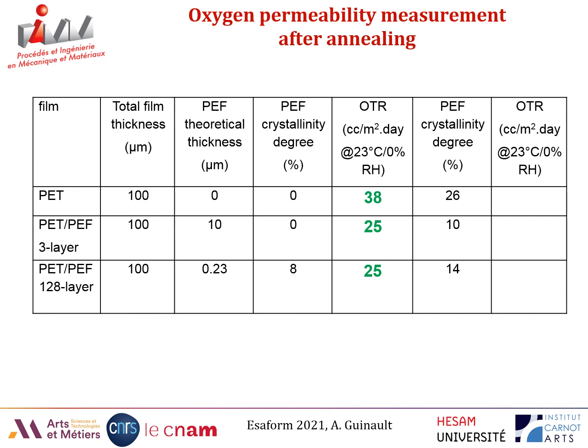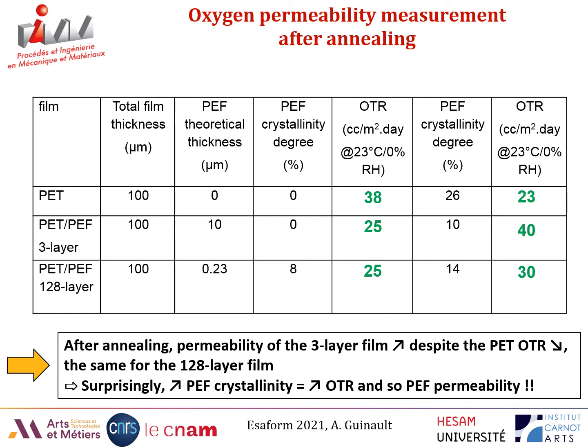Now we can see the effect of the annealing and the increase of crystallinity on the gas barrier properties of the films. So you can see that for PET, when you do an annealing, you decrease the oxygen transmission rate from 38 cc per meter square per day to 23. But for PET-PEF 3-layer and PET-PEF 128-layer, the value finally doesn't decrease but increases. So after annealing, you can see that surprisingly, if you increase PEF crystallinity, you increase the oxygen transmission rate and the PEF permeability. That is not a classical result.